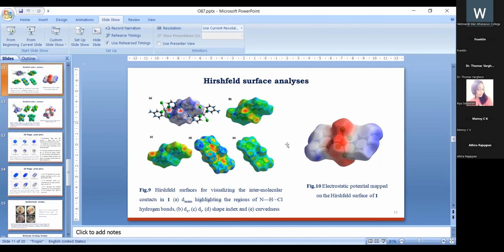Figure 9 shows the Hirshfeld surfaces plotted on different properties, and 9a shows the d-norm surface of solid 1. And here, the bright red circular spots on the Hirshfeld surface indicate the regions involved in hydrogen bonding interactions. Similarly, 9d is a shape index map. And on this, we can see adjacent triangular blue and orange patches over the aromatic ring, which indicates the presence of weak pi-pi interactions in the crystal.